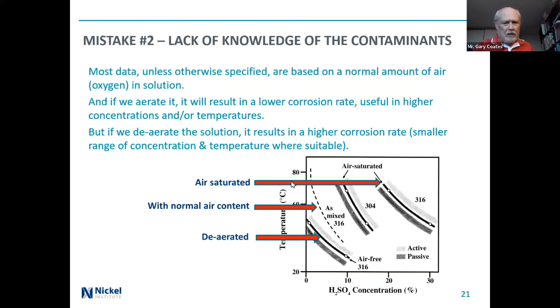So the top red arrow shows 316 where we air saturate it, we blow air into the material, and again you get a much higher useful range where you can use 316. If it's normal air content, it's this line, the same line we looked at earlier. And if we de-aerate the solution, 316 is used at a much smaller area there. So maybe 10-12% for air free de-aerated sulfuric acids.